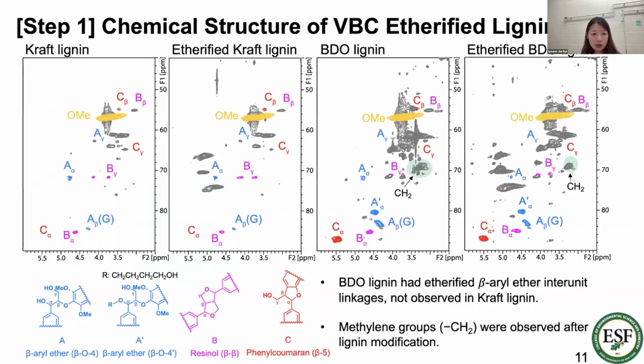And we measured 2D-HSQC NMR to see the chemical structure of the modified lignin and the raw lignin. As we mentioned before, the BDO etherification showed up for the BDO lignin compared to the kraft lignin. And after the modification, we observed that new peaks showed up related to a methylene group. But the lignin structure we use has a large molecular weight, and it's hard to define which part is exactly modified.